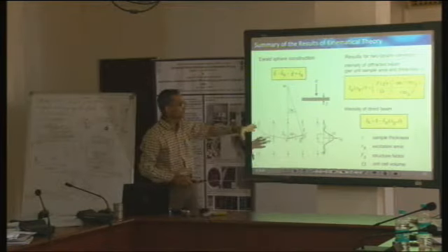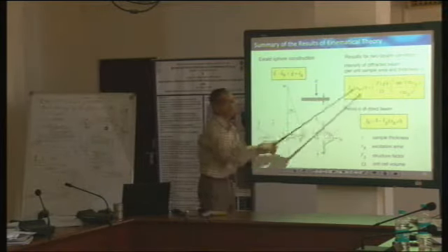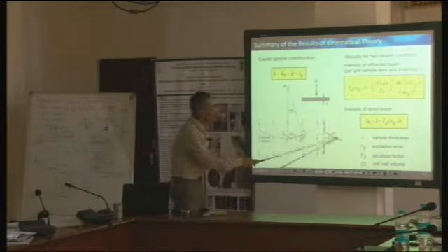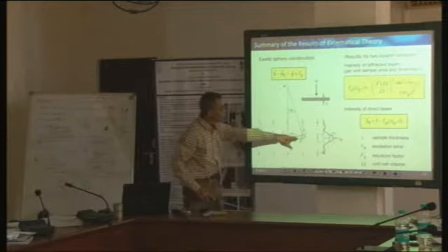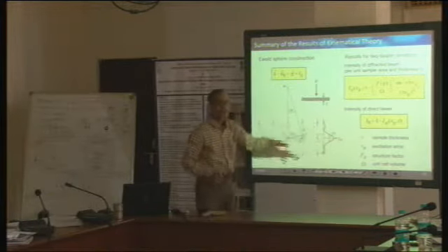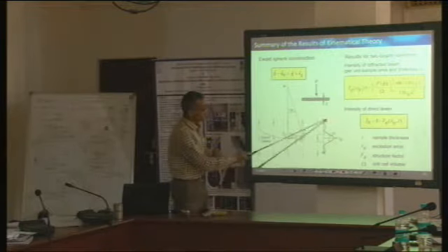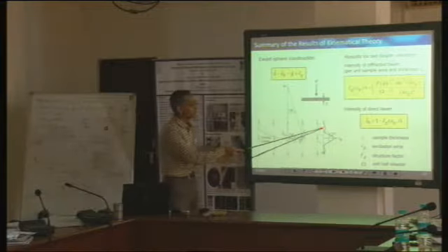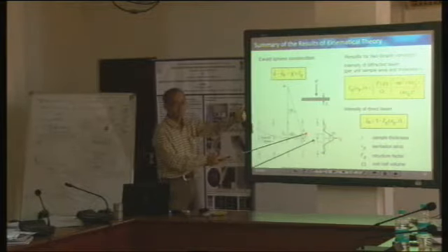So I have the maximum. And if you plot this function as a function of S, this is what you will get. At S equal to 0, I get maximum intensity, and as I go away from S, the intensity decreases. But there are also additional secondary fringes, which means that for a particular S you again get secondary maxima and so on.